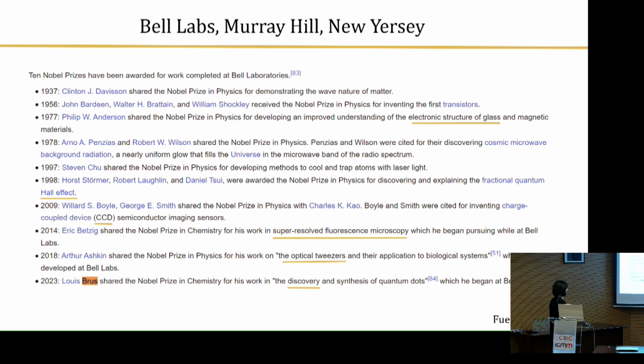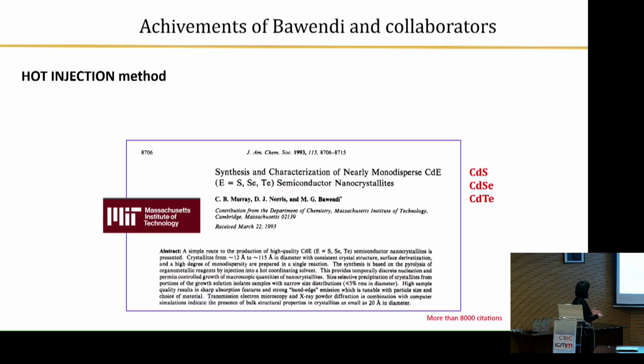Not bad. Okay, so going with the achievements of Bawendi and his collaborators, what they published is a methodology to produce nanocrystals very easily, in principle, controlling all parameters in a way that you can control the size and the polydispersity of the sample. So you can produce crystals which are very similar, let's say with very narrow size distribution, out of this method.